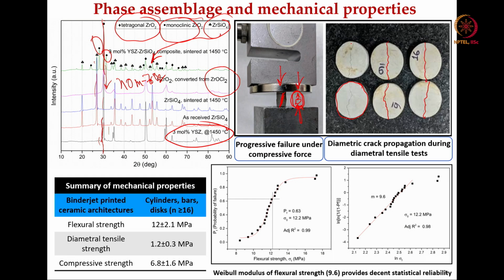Suppose in the diametral compression test the crack propagates randomly, like the way I am drawing. This is not good. If you see that kind of evidence after the fracture is over, then it should be clear that it will not give you a reliable tensile strength from the diametral compression test. The ideal evidence is crack propagation along the diameter.